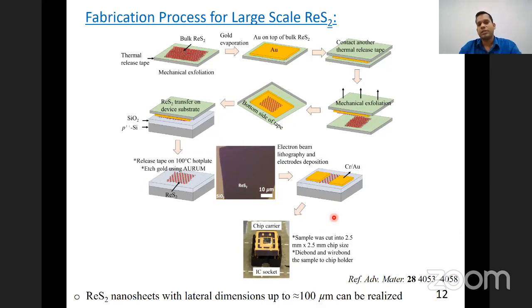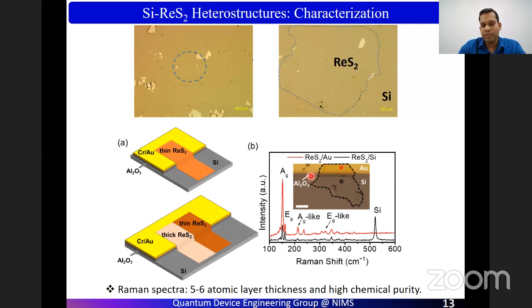This technique describes how we fabricate large-scale ReS2. We basically use the gold-mediated exfoliation technique, which is described in this reference. And we can even get a large area of ReS2, more than 100 micron by 100 micron, and we can have device fabrication and finally chip integration for real applications. Once we deposit rhenium disulfide on a silicon substrate, you can see there is almost no optical contrast, so you cannot even see it. But if we use this initial template, then we can deposit in a particular area.